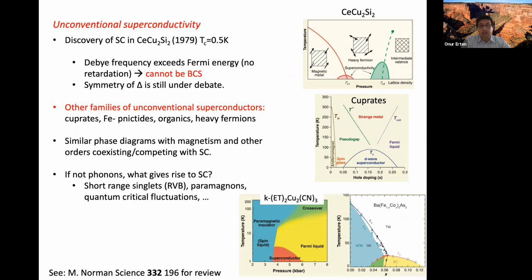And so you might ask, if the effective attraction is not due to phonons, what gives rise to superconductivity? And again, this is still controversial, and there are different theories; they are usually near some magnetic order. So people think it might be due to short-range magnetic order, like short-range singlets. This is Anderson's idea of resonating valence bonds. This is more like a strong coupling theory, or in the weak coupling, people think about paramagnons. Paramagnon means that magnons are the low energy excitations of magnetic systems. So paramagnons are almost like a magnon, some collective excitation of things that do not really order.